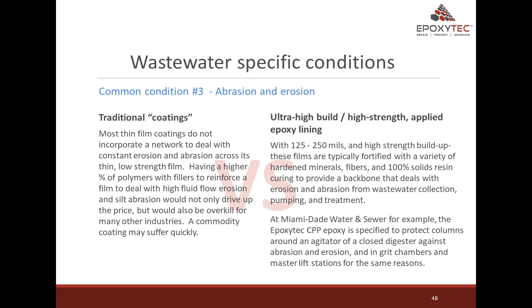High build epoxy, CPP. With 125 to 250 mils, a high-strength buildup of these films are typically fortified with a variety of hardened materials, fibers, and 100% solid resin, curing to provide a backbone that deals with the erosion and abrasion from wastewater collection, pumping, and treatment. At Miami-Dade Water and Sewer, for example, the Epoxytec CPP epoxy is specified to protect columns around an agitator of a closed digester against abrasion and erosion, and in the grit chambers and master lift stations for the same reason, as was evident in one of our case studies that we reviewed earlier.